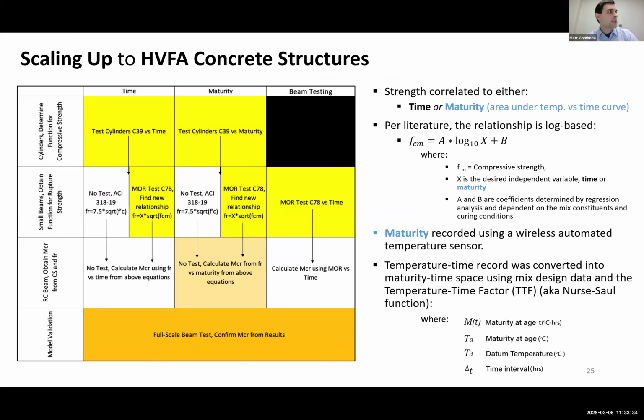The other aspect of the story then was how to take these results and scale them up to structural design. And we came up with this framework here that is in another paper that my student and I published, that looks at how to use different methods using both the plots of concrete strength versus age that I showed earlier, but also now incorporating some maturity testing to monitor the temperature in the concrete to help correlate the strength gain properties in the member back to what we had when we did the tests on the specimens in the first place.